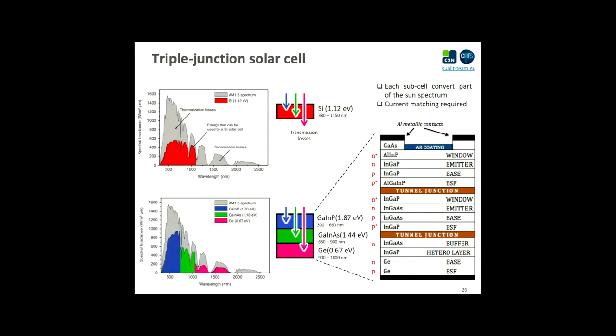How does a multi-junction solar cell work? The idea is that you have 3 solar cells with 3 different adapted gaps. The higher bandgap will be here, and will absorb only the blue photons, leaving the green and the red going through to the second and the third. And by doing so, you are basically reducing the thermalization losses. Those are normally connected in series, so it's a 2-terminal device. And in order to make it work, you need to have the same current through the same cell. So we have to calibrate properly the bandgap and the thickness in order to have the same currents through the same device.